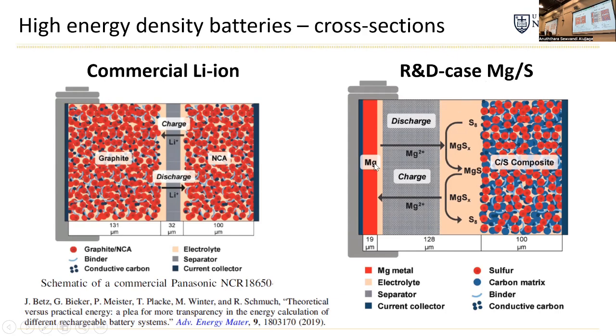I'll just point out in this cell, you can see here that instead of graphite on the anode, we've replaced it with magnesium metal. So by using the pure metal, you can really reduce the scale of the anodes. You don't need very much material. But magnesium sulfur electrochemistry is pretty challenging.